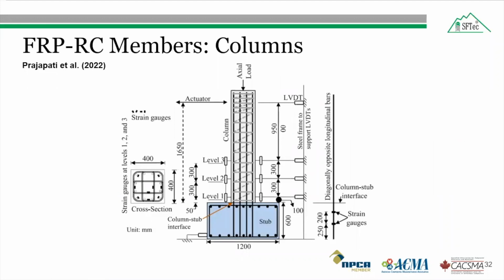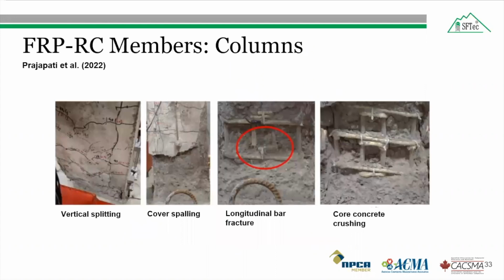Now coming to the columns. Reinforced concrete columns were tested to study the confinement effect of glass fiber reinforced polymer spirals and cross ties on concrete columns longitudinally reinforced with GFRP or steel bars. The failure mechanism for the first tested GFRP reinforced concrete column: the first crack occurs, and after that, more tensile cracks begin to appear on further drift cycles. The concrete cover starts to split vertically, and on further increment of the drift, the concrete cover starts to fall. Longitudinal reinforcement interlaminar degradation was seen. After that, there was a fracture of the longitudinal GFRP bar in compression. On increasing the drift, the cross tie ruptured, and finally the core concrete began to crush.